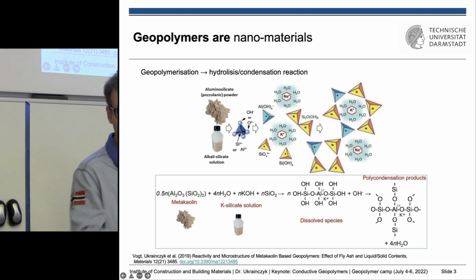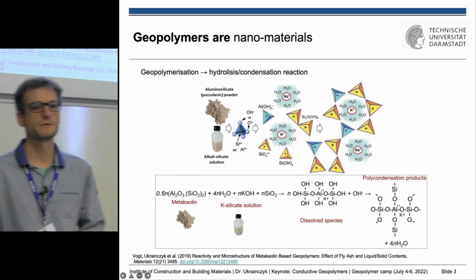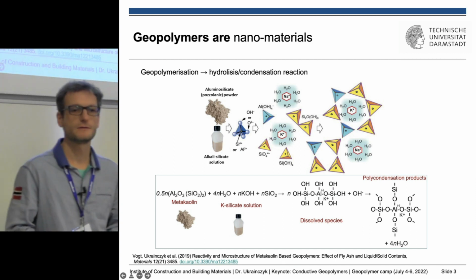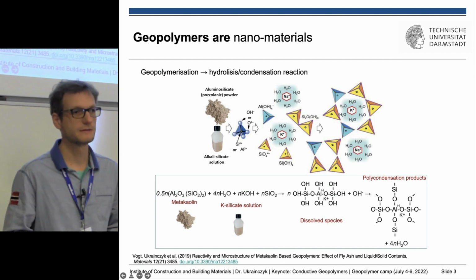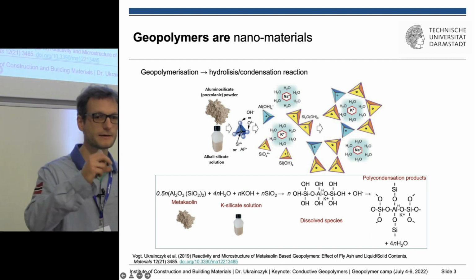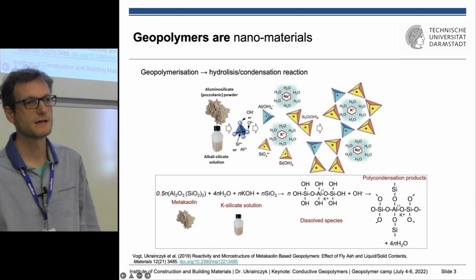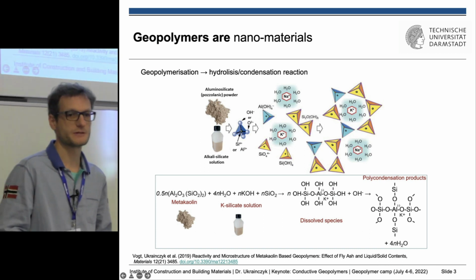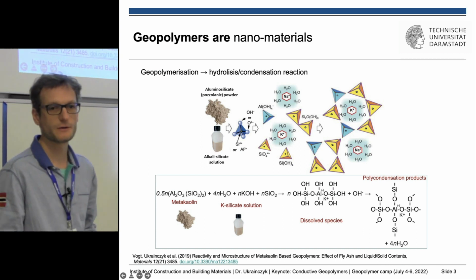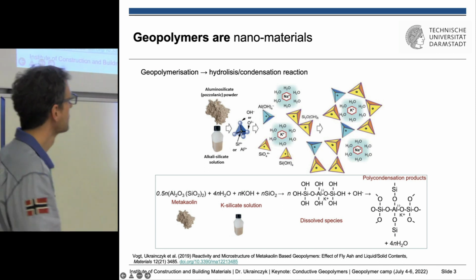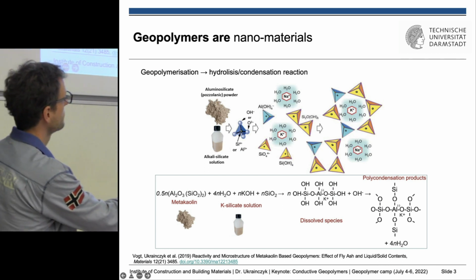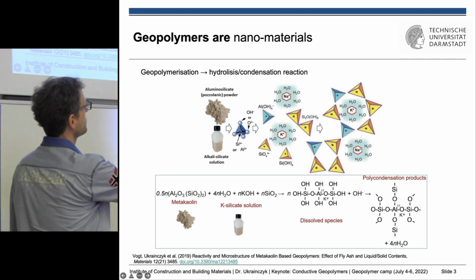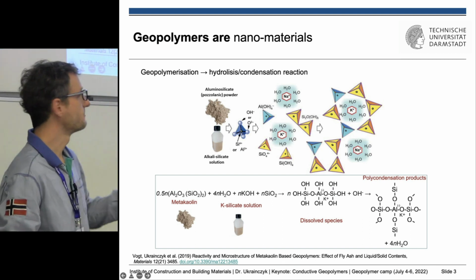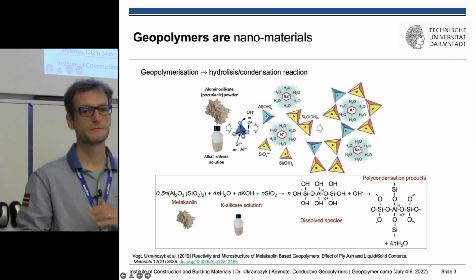micelles, which are on the order of 10 to 20 nanometers, which then aggregate, and then they form nice porous structures, which we would like to tailor to have different porosities. And this is also a reversible reaction, I should mention. So depending on the pH, it can go back and forth.